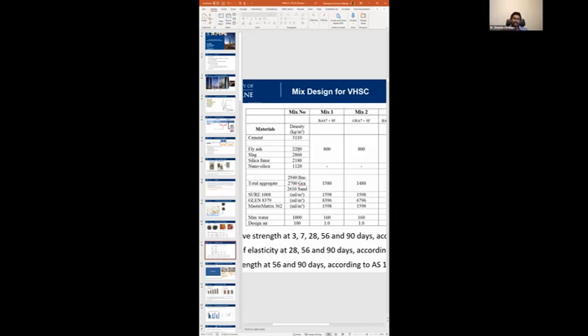One is that there is less water, and water actually does not have strength. If you indent water, it has zero strength. So less water means fewer pores, less zero-strength material, and we have more unreacted fly ash and slag particles, so it will add strength as well. Normal strength concrete is weak because of too much water, more pores, and we are also creating more low density, porous CSH. In very high strength concrete, less water means the CSH is denser.